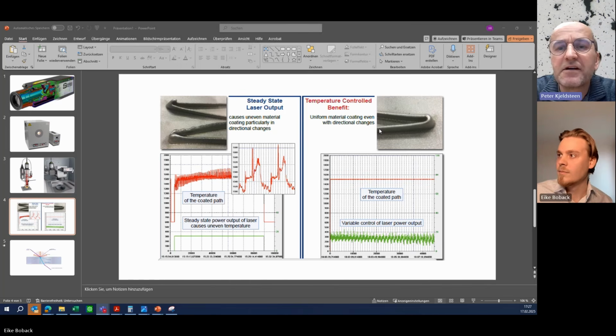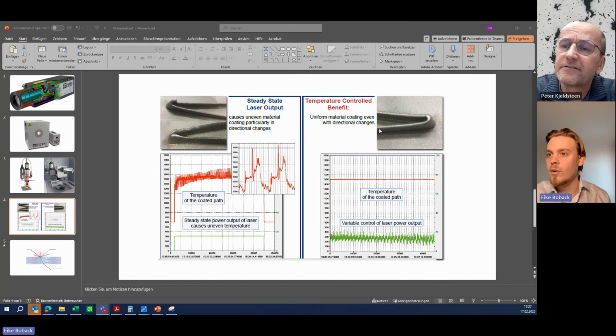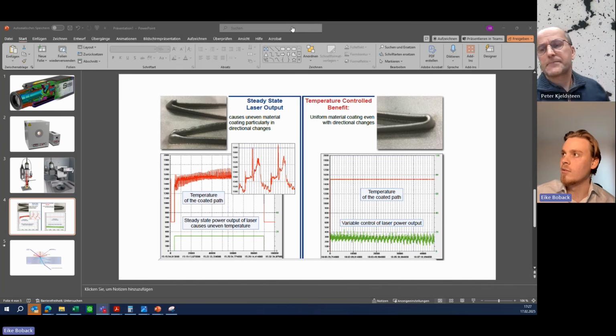That's pretty smart. And you can control it down to 200 microns in spot size, you said? Yeah. So it only depends on the spot size and the speed you go. If you have a big spot size, the speed can go faster, and the other way around, if we have less speed, we can go to smaller spot sizes.